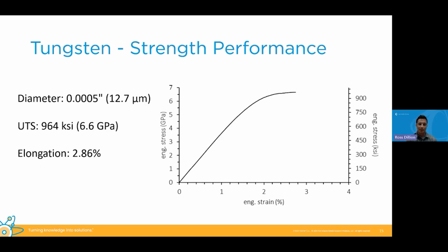As I noted, the 800 plus, this is where that plus comes in. We're able to almost hit 1,000,000 PSI at 12.7 micron in diameter, and still, again, maintaining excellent elongation. So this is basically the highest recorded strength that we could find for commercially pure tungsten.